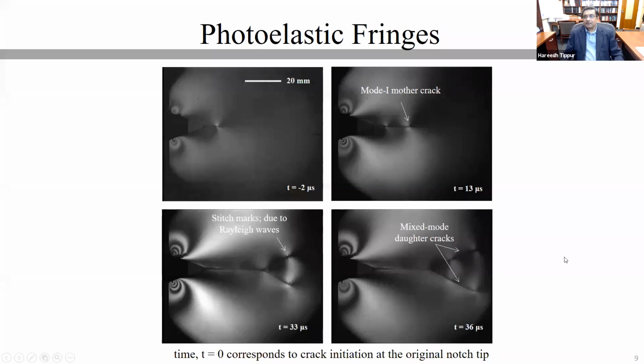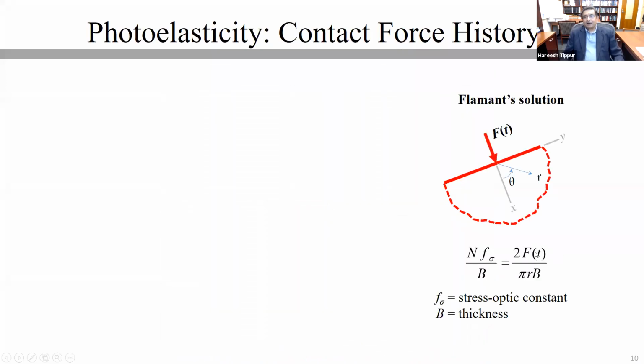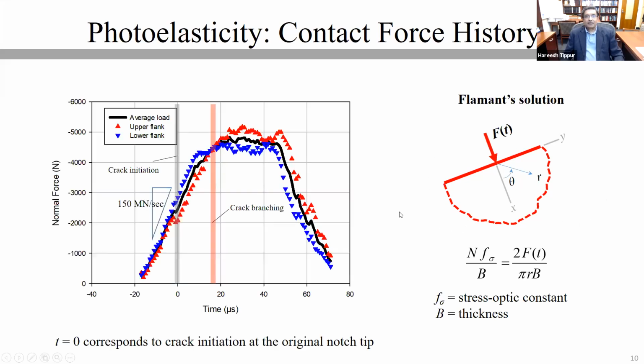fringes themselves. You can also measure the load history, force history that you have imposed on the specimen using a simple approximation based on Flamant solution. And you can back out the force history by analyzing all those fringes that you saw. Normal force as a function of time here. And you can see that the loading produces some sort of a trapezoidal type of loading. The first bar that you see, the grayscale, is for when the crack initiated, and the red is for the place or the time when the crack branched.